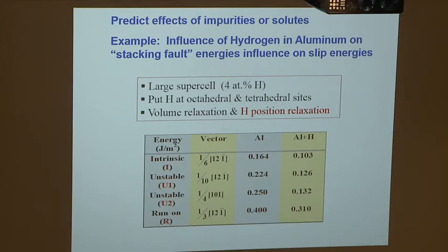So you don't have to guess what the hydrogen is doing. You calculate the properties of aluminum, you calculate the properties of aluminum with hydrogen, and you see that some properties of the material change, right? And this kind of thing, you can't guess what this should be, but you can calculate it.